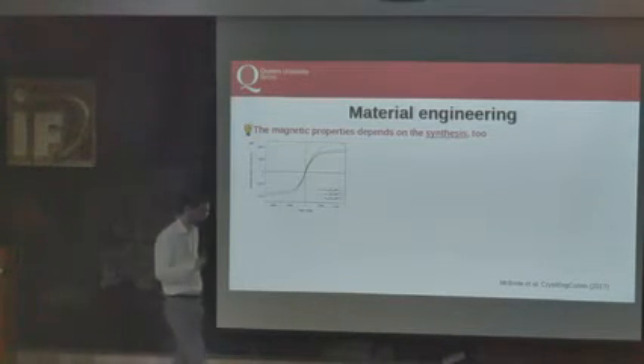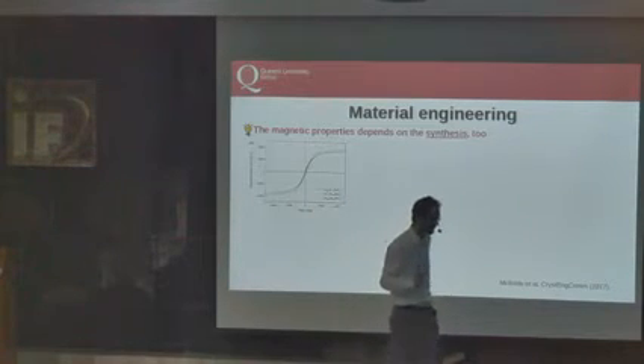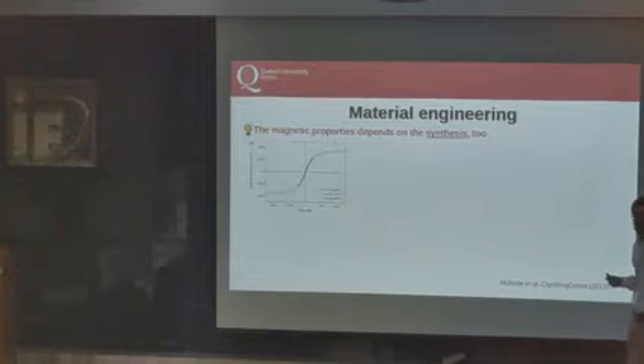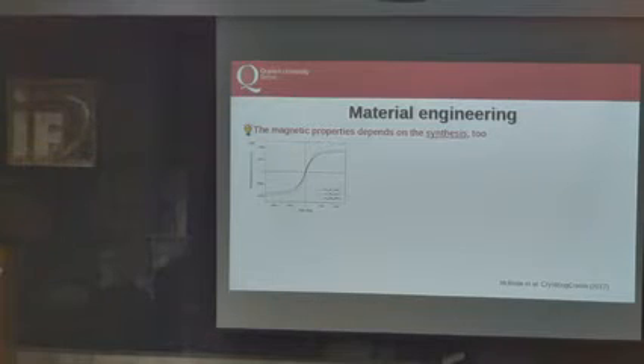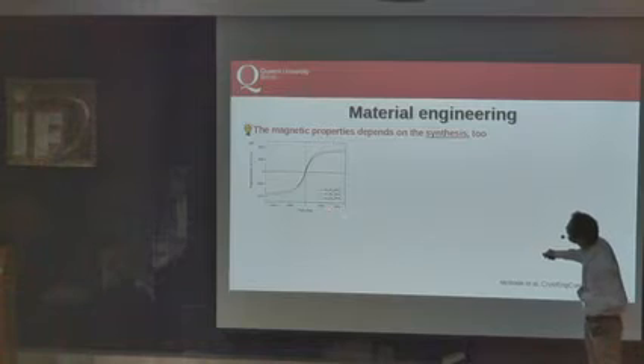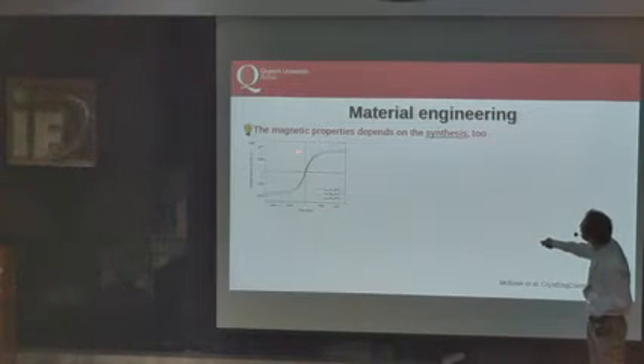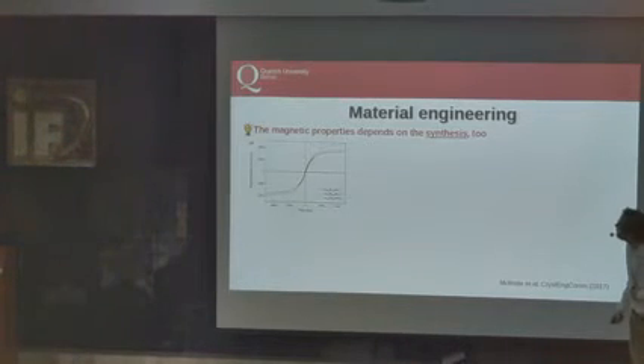Okay, life is much more complicated than that. Those magnetic nanoparticles were synthesized with the sol-gel method, so there was a solution of the various oxides. Details must be asked of the experimentalist. The solution form was a sol, then the solvent is extracted, and there is a nanostructured gel. This is dried out, calcinated at high temperature, then ground, and this gives the LSMO nanoparticles in the conventional way. And you can see the saturation magnetization is about 4,000 EMU per mole.